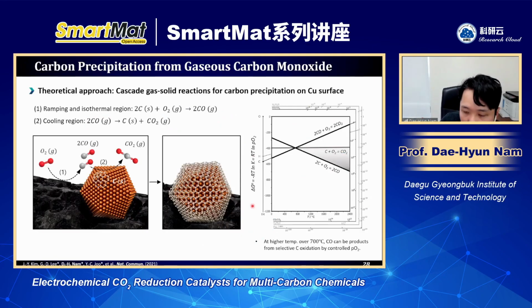So at first, we wanted to suppress and prevent this kind of reconstruction. And we thought we wanted to make a protective shell, which can prevent severe structure and phase evolution during the CO2RR. So we focused on fabricating a carbon shell on the surface of the copper. This is different from the conventional method, because if we just deposit carbon on the surface of the copper, it can block the active sites.